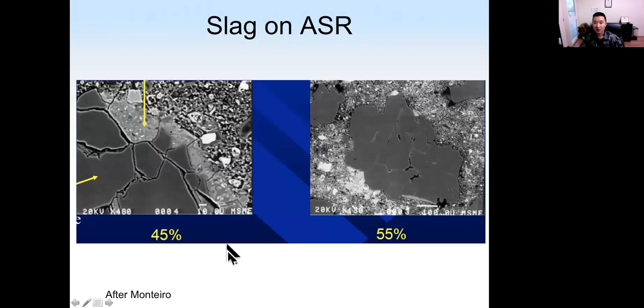Okay. Again, this is from a scanning electron microscope. The cracking due to ASR, 45% of that, we see more cracking compared with 55% of slag.